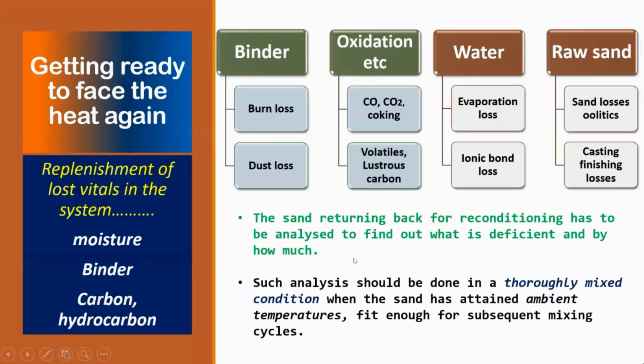Such analysis should be done in a thoroughly mixed condition when the sand has attained ambient temperatures fit enough for subsequent mixing cycles. Here, the thoroughly mixed condition is important as well as the ambient temperature. You can't take out a return sand which is very hot and then check it, because by the time you bring it to the lab, some moisture will be lost. So you would not know what is the actual moisture content in that sand. Similarly, if you are not mixing it thoroughly, you will not be able to assess what is the remaining part of the binder, remaining part of the coal, remaining part of the sand.